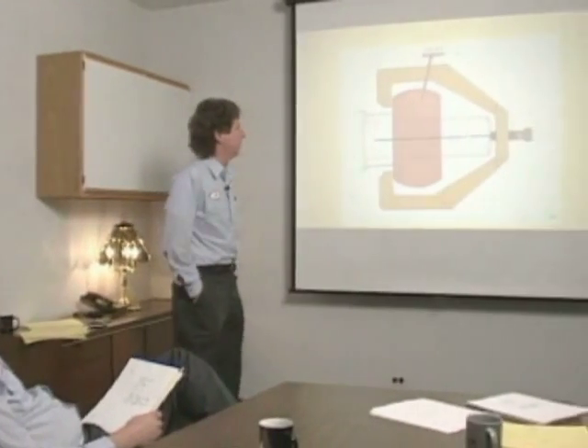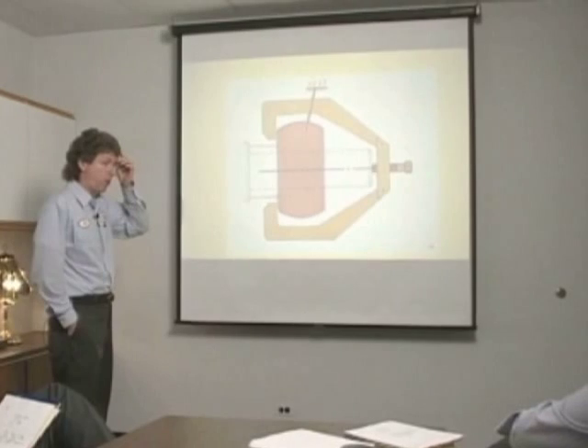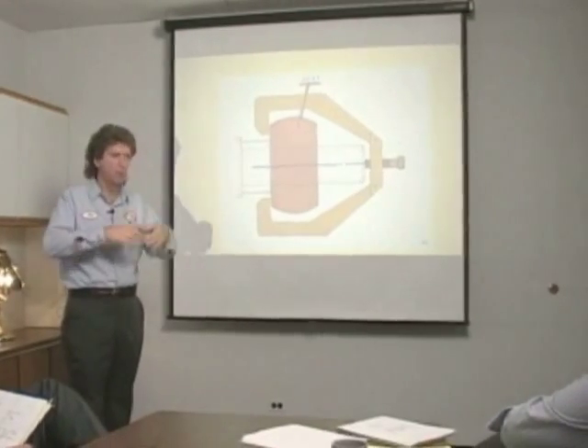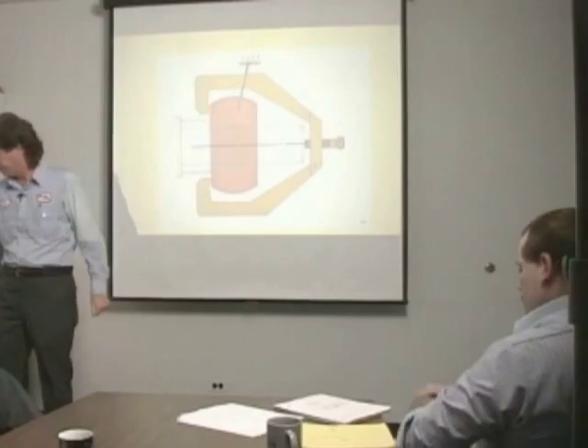Am I going to damage the roll when I heat that up? Yeah, sometimes if you just keep the heat going around it, you may soften it a little bit, maybe a half a point or a point. But most of the time you don't turn it red, of course. We're looking to heat the roll so the heat expands. And when it expands off the roll, you can take it off. So it works out pretty good.